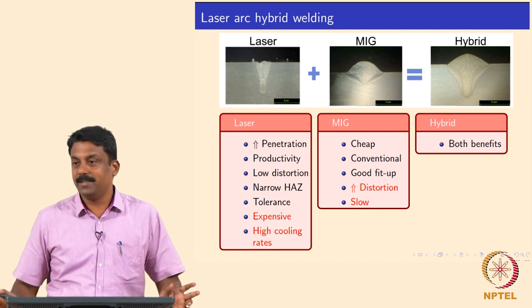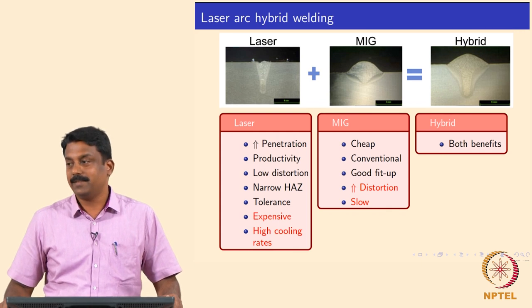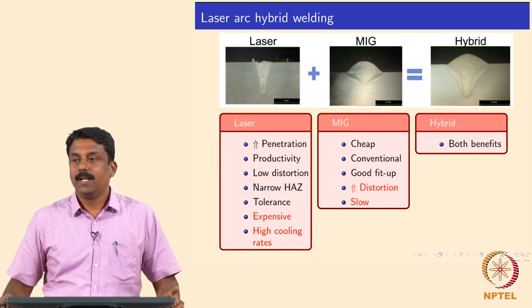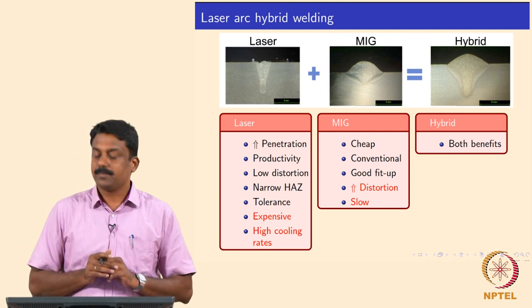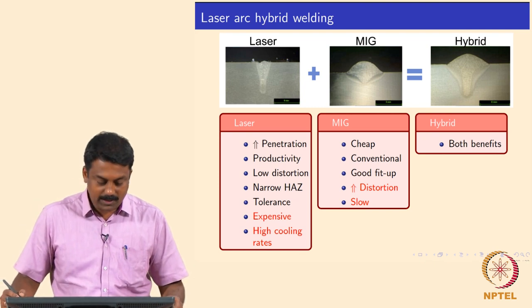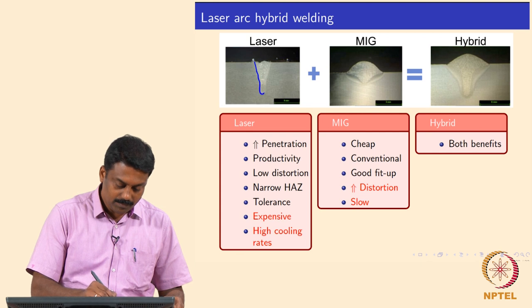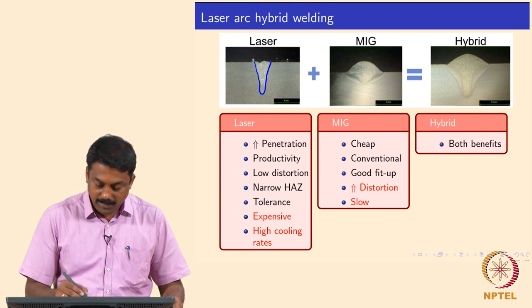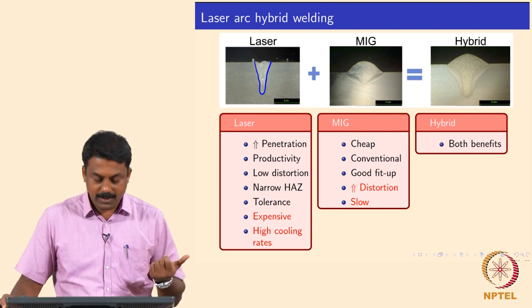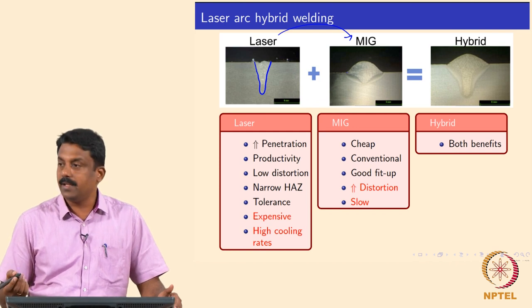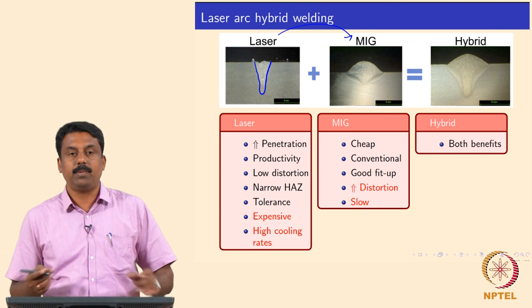There are attempts to combine laser and arc. In arc welding the penetration is very poor because the power density is very low. In laser welding, power density is very high but you have a very narrow weld. By combining these two, we can achieve larger penetration and a slightly wider bead. As shown in this slide, using laser alone gives you a keyhole but a very narrow weld, and using only GMAW gives a wide bead but very poor penetration. Combining them achieves a wider and deeper weld.